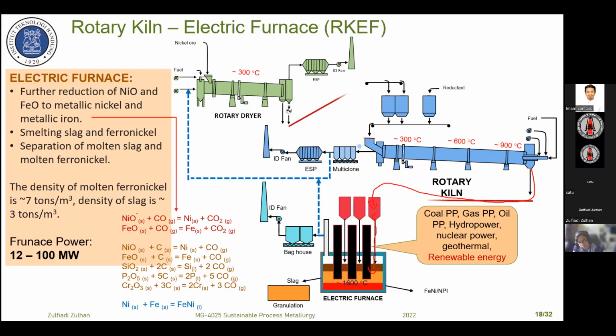In the electric furnace, the nickel oxide is further reduced to nickel metal by CO gas. The CO gas will be formed at the bottom, at the center here of the electric furnace, and during the moving up of this gas, the nickel oxide in the calcine can be reduced to nickel metal. If you see, the main composition of the off gas is still CO.